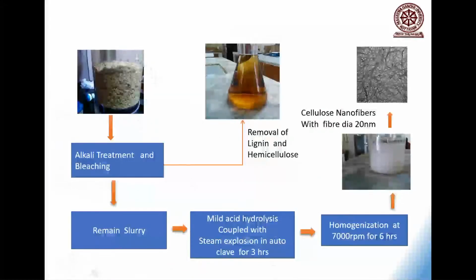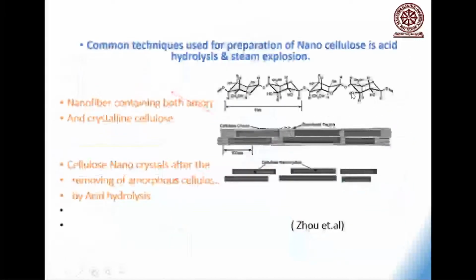I can show you what we do in my laboratory. My PhD students collect agro waste, go for an alkali treatment and bleaching. You remove the lignin, you get a slurry. You go for a mild acid hydrolysis or a strong acid hydrolysis, depending upon what you really need. If you are interested in long nanofibers, we go for a mild acid hydrolysis. If you are interested in short nanocrystals of cellulose, we go for a strong acid hydrolysis. And you see finally what we get. This is under electron microscopy, high resolution electron microscopy. We get beautiful nanofibers.